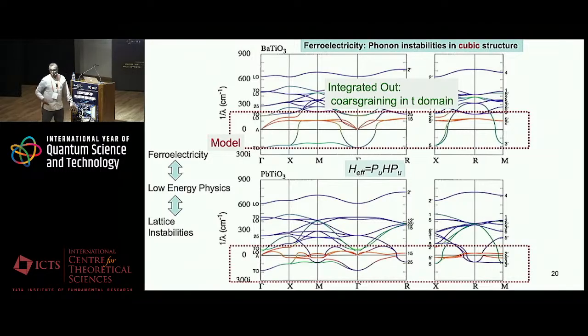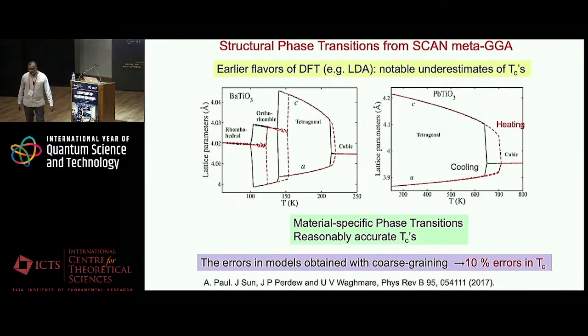The effective Hamiltonian we work with is a projection of the full lattice Hamiltonian into the subspace defined by these modes. How we do this projection is another technicality, but we basically use phonon Wannier functions for that projection, which assume simple interactions between higher energy and low energy phonons. Using this approach, we can predict phase transitions. Now you see the success of this theory.